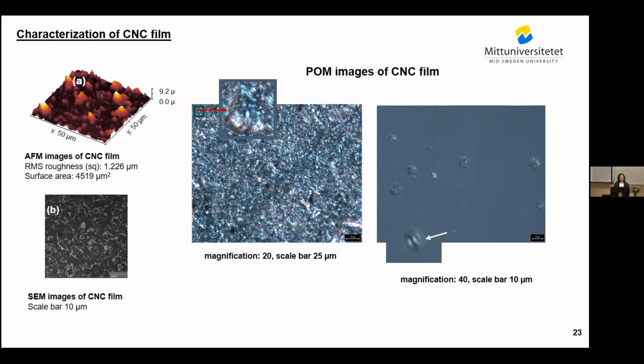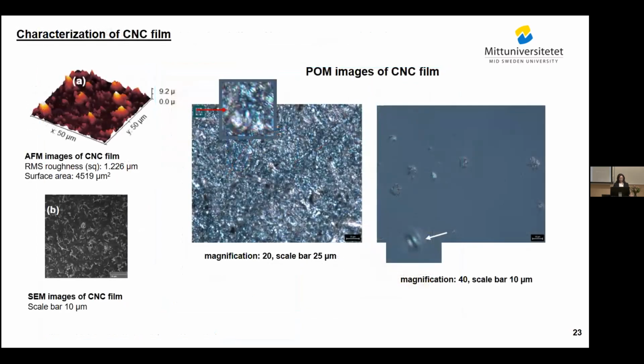Characterization of this prepared CNC film with AFM shows a surface roughness of more than 1.2 micrometers. Polarized microscopy of this surface shows that we can see the chiral nematic phase, with a film thickness of 40 to 45 micrometers. Then I magnified the same surface 40 times to see exactly what is at the surface, and here we can see newborn tactoids. Here they are everywhere, and also growing tactoids and the fusion of tactoids. It means that with the filtration system and the self-assembly feature of rod-like CNC during concentration, I could prepare a surface with a roughness of more than 1.2 micrometers.